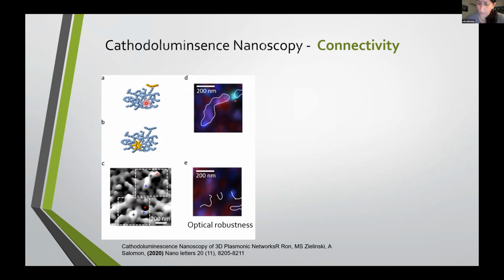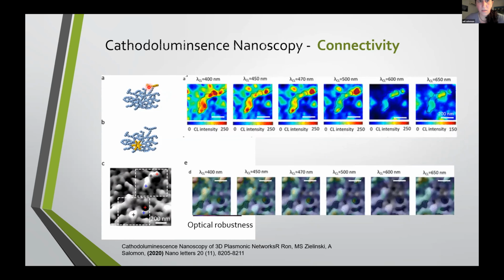For example, if we have an element which has only one connection to the network, we see a very clear localized mode, whereas when we have a kind of octopus structure which is connected all over, the energy is dissipated and we barely see emission in this region, which reflects the optical robustness of this network.